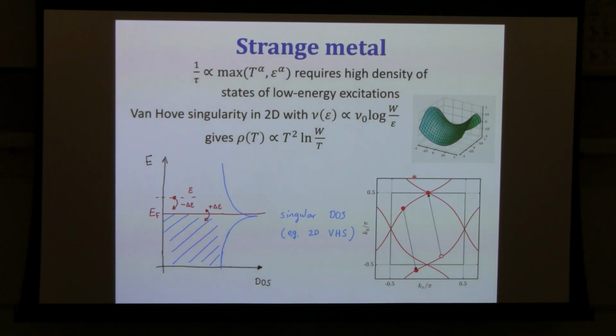Okay, so now this is a little bit counterintuitive because all the pileup of low energy density of states is happening at one point or a few isolated points in momentum space. So it looks like transport would not be sensitive to these isolated points. The electrical current is carried by the entire Fermi sea, not just by the parts of the Fermi sea that are close to these Van Hove points. But it turns out that the possibility to scatter electrons into these points with a very high density of states can actually affect the relaxation rate of the current over the entire Fermi sea.